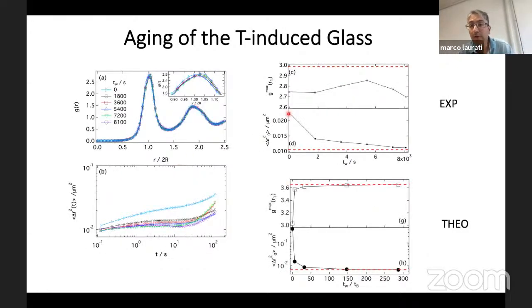But then another question that we asked ourselves was whether the difference between the glass formed by decreasing the temperature and the glass formed through the concentration route was again an effect essentially of different aging of the system. So what we did was take the glass formed through the temperature route and let it age for longer times and follow the evolution of the structure and the dynamics of the system as a function of this increasing aging. And we found, I would say, something interesting.